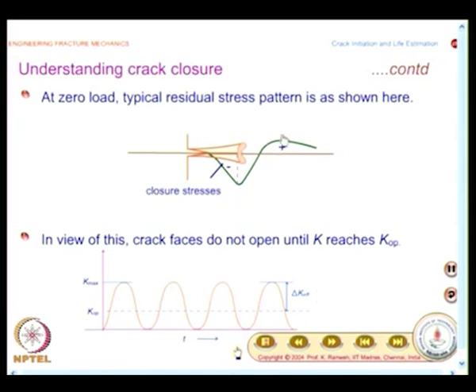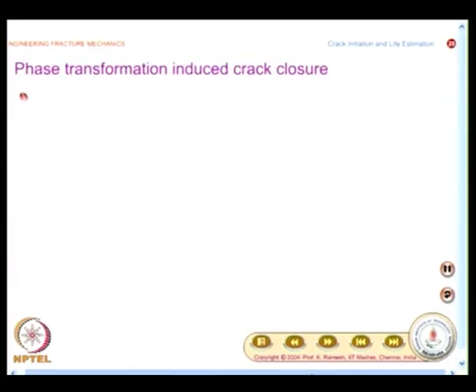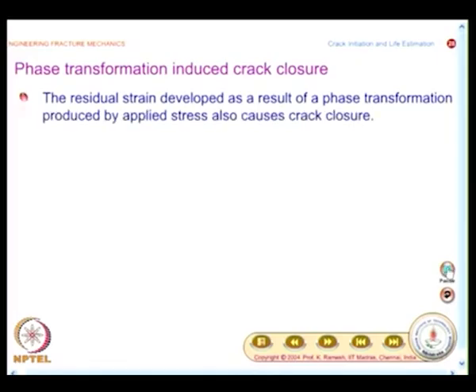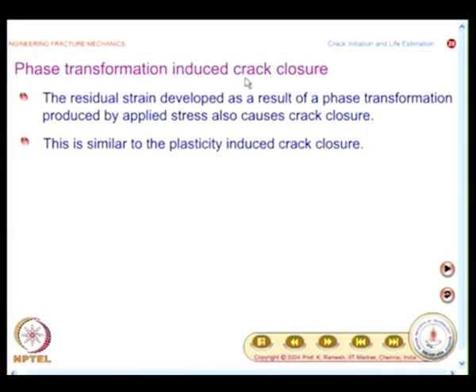Once you have appreciated this, there are also other models that are given which are easy to understand on a similar logical framework. Crack closure can also happen because of phase transformation. The residual strain developed as a result of a phase transformation produced by applied stress also causes crack closure. The physical appreciation of the phenomenon is very similar to the plasticity induced case.